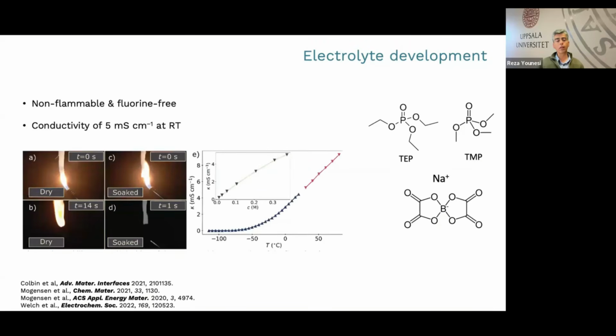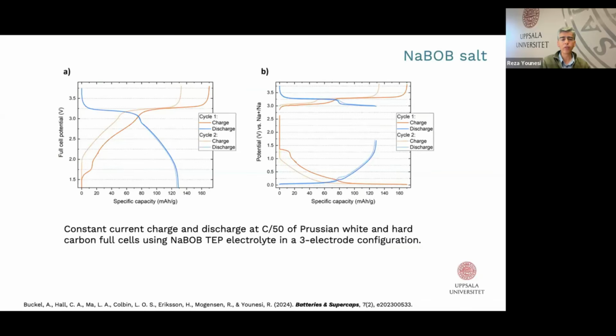We have been working on this electrolyte in the last few years, aiming to improve safety and sustainability of sodium-ion batteries. The interesting thing with this electrolyte is that if you make a full cell of hard carbon versus Prussian white using this electrolyte, NaBOB in TEP, on the left you see the first cycle and second cycle in a 2-electrode cell, and on the right you see the three-electrode measurement showing each electrode individually.